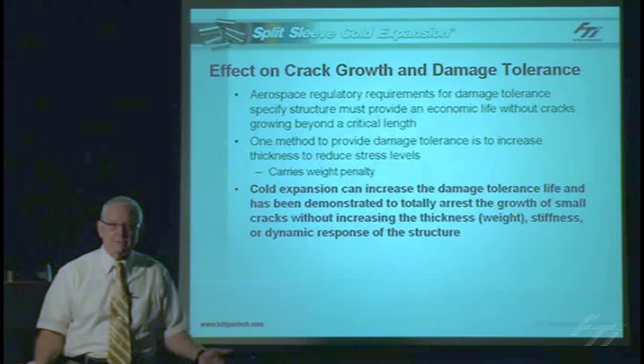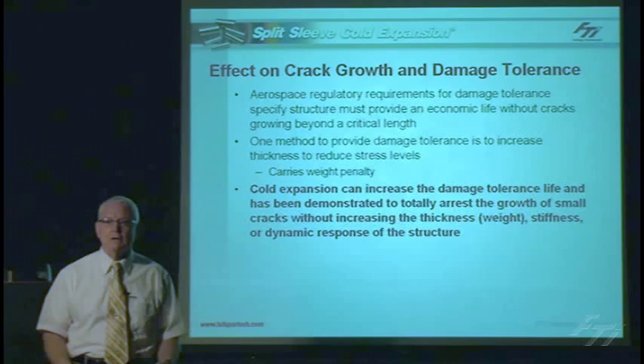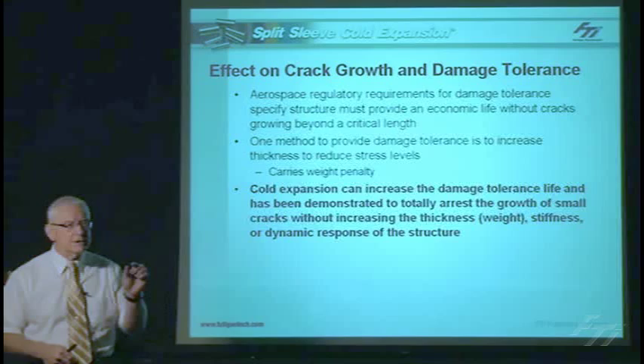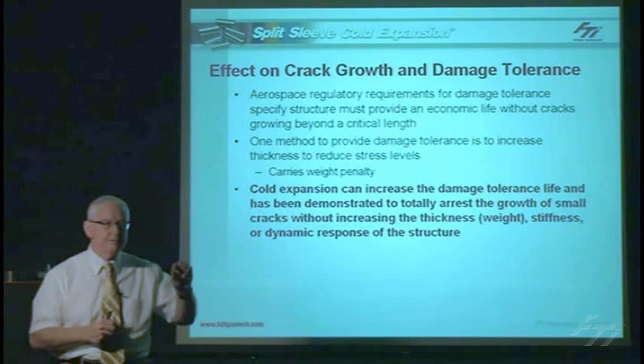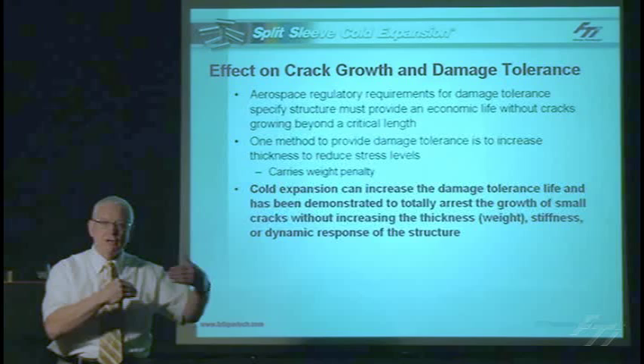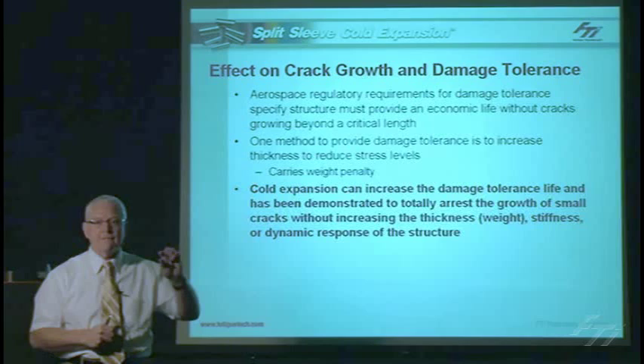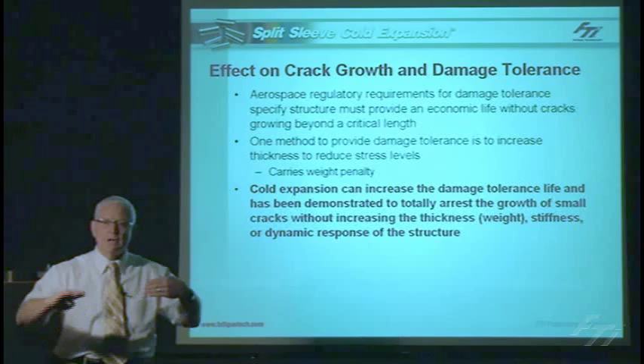What happens in damage tolerance? As all aircraft fly, we're going to generate fatigue cracks in fatigue critical holes. How can cold expansion improve the damage tolerance — that is, the life with a pre-existing crack? Most airworthiness authorities and the military require you to do an analysis assuming there's a rogue flaw, even in manufacturing — someone may have put a defect in, or there may be an inclusion in the material. That rogue flaw is typically in the order of about 50 thousandths of an inch. So you assume that's there and do your residual life analysis based on that residual crack.